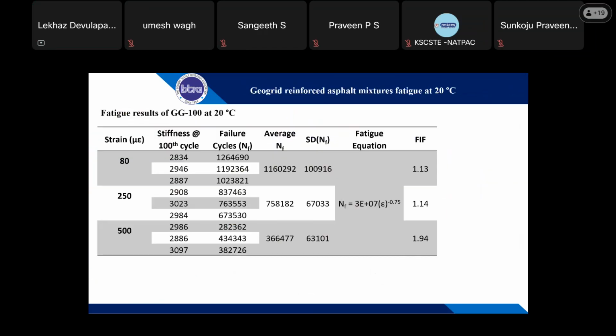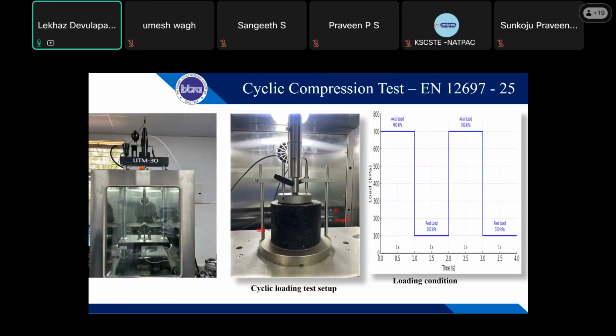So we've seen we have a good improvement in terms of rutting and fatigue, and then we want to do a cyclic compression test on the pavement. This test will give you the actual loading condition of traffic. Here you can see a UTM was used to do the test, and we have prepared gyratory samples of 150 dia. We place this in a temperature cabinet where we can control the temperature. This test is done at 40 degree.